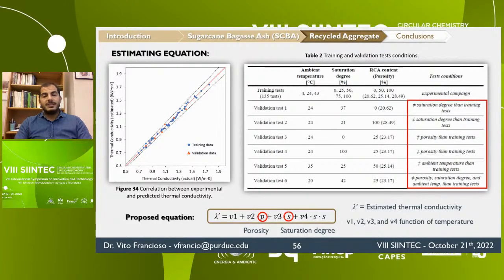The accuracy of this model was also validated through several additional tests, where training data as well as arbitrary values of ambient temperature, saturation degree, and porosity were tested. And if you remember, at the beginning I said that the mixtures with 25% replacement of recycled concrete aggregate we didn't use for the thermal conductivity. We actually used those samples to validate this model, to validate this equation.